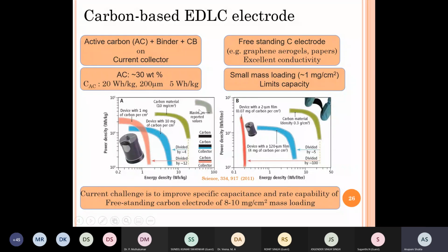active electrode is. Okay. The other way to construct electrode is to have a freestanding carbon electrode. Okay. People have reported graphene aerogels, papers, carbon paper. These have excellent conductivity. So why a current collector is used is because this activated carbon is a porous material, and a porous material has even more reduced conductivity, because the paths for electron conduction become fewer as much of the space is occupied by the pores, and therefore a current collector is required, otherwise there is a lot of contact resistance. However, if one uses these materials like graphene aerogels, papers, they themselves have excellent conductivity, therefore a current collector